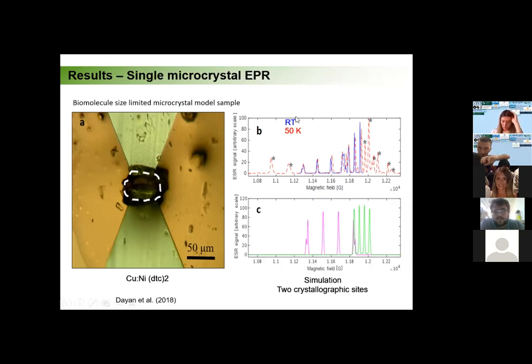And this is a bit of a problem when we go to low temperatures, because the actual substrate has some spin radicals that are in the way of our measurements. The way that we solve this is to replace the substrate with a silicon substrate, and then we have less impurities, and it's easier to do low temperature measurements.